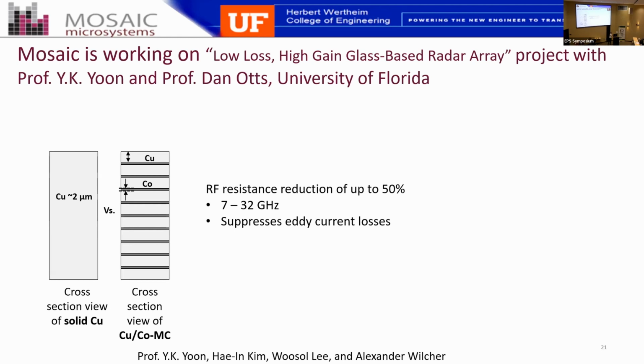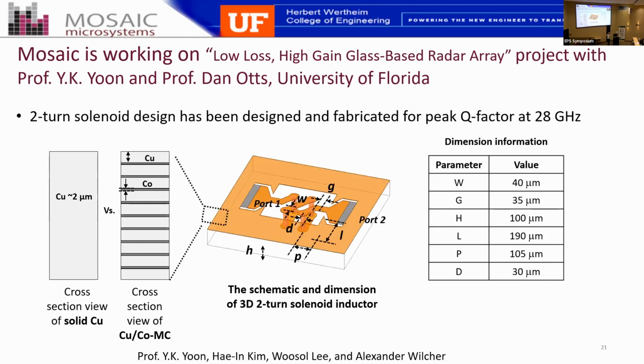And so what we're doing, as part of the characterization before we go and make the actual radar arrays with this, is make some two-turn inductors to characterize the Q factor of these and verify that we're actually seeing the improvement with this low loss material. So if you're into that kind of thing, you can see the dimensions of the material here, and in this case it was a 100 micron thick piece of glass. So the TGVs are part of that inductor loop.